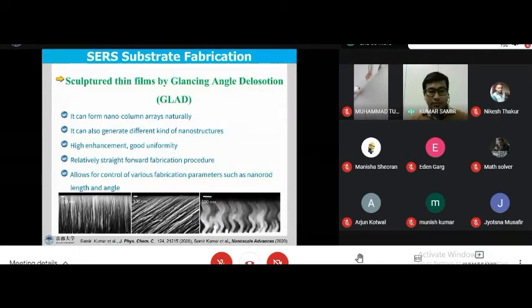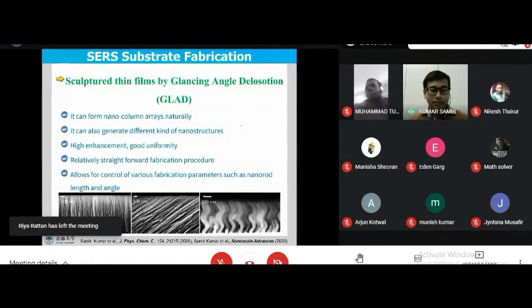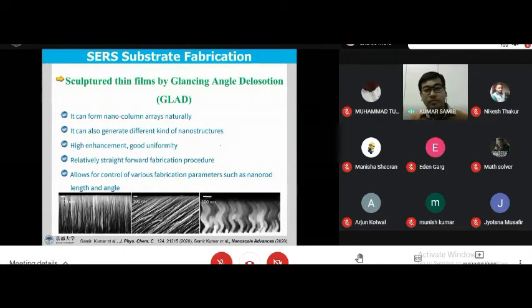The advantage of using glancing angle deposition is that it can form nanocolumn arrays naturally. So you don't need any highly expensive lithographic techniques or any seed layer. You can use a seed layer also for more uniformity, but it is not necessary. You can also get these nanocolumns without a seed layer. And second, using the single technique, you can generate different kinds of nanostructures for the same material, with high enhancement and good uniformity. And since it is a physical vapor deposition technique, it is a straightforward fabrication method with lots of control over different parameters.